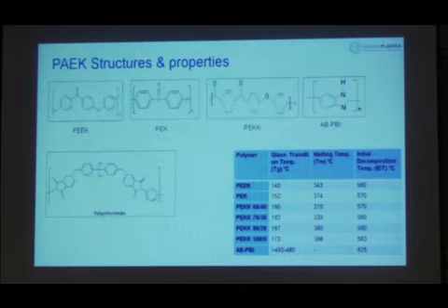So first three are polyaryl ether ketones. So you can play with ether and ketone linkages and the ratio. And when you change the ether and ketone linkages, you can change the glass transition temperature, and you can play with the continuous heat temperature resistance and melt temperature, processability, stiffness, and all this. You can play around with that.